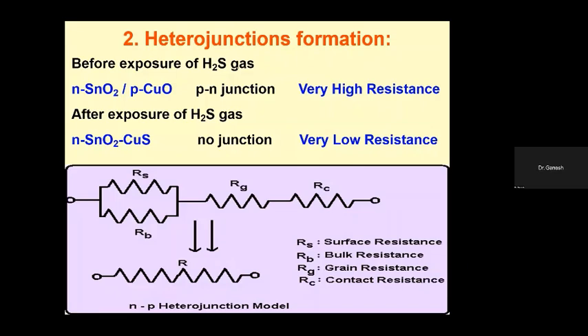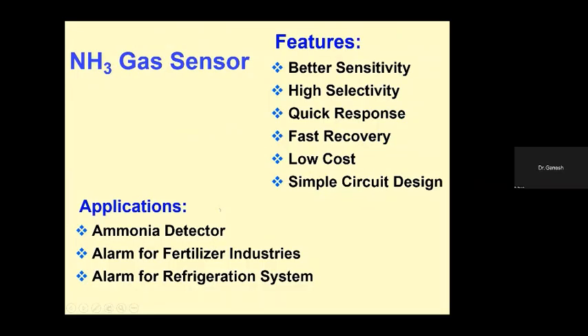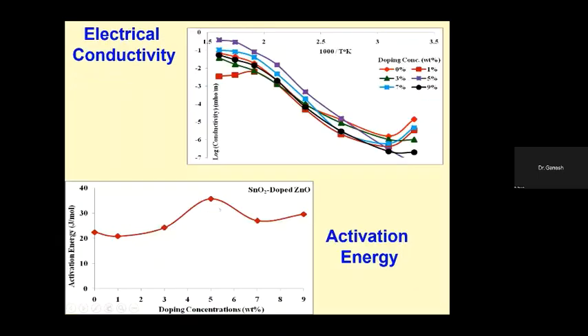So this is another mechanism, heterojunction formation. Before exposure to H2S gas, the n-SnO2/p-CuO junction shows very high resistance. This is the resistive model of the sensor. And once the H2S gas is exposed, the p-type CuO gets converted into conducting CuS and ruptures the p-n junction, becoming very low resistance. So here the ammonia sensor is there, with IV characteristics and conductivity.